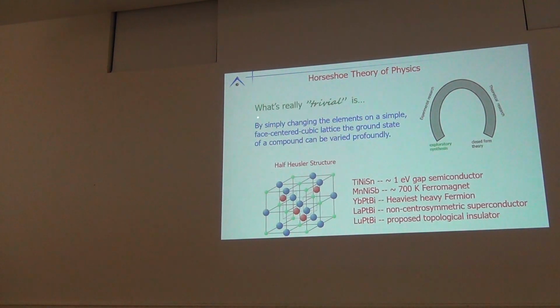Well, what is trivial, at least for me, is on the experimental side: I can take a simple structure, the half-Heusler structure, which is sodium chloride plus 1, a simple cubic structure, and I can decorate this with different atoms. I can go from TiNiSn, which is a semiconductor, to MnNiSb, a ferromagnet, heavy fermion, non-centrosymmetric superconductor, topological insulator. That is trivial. You're just changing what you decorate, and you completely change the state. So these two extremes of physics are actually closer than you may appreciate.